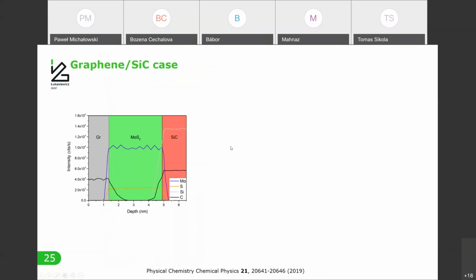However, the most interesting part was when we tried to repeat the same experiment to make the molybdenum sulfide film on top of a graphene which was CVD grown on silicon carbide. We grew it on top of graphene, and to our surprise, the result was that, as you can see on the depth profile, the molybdenum sulfide film was actually formed below graphene.